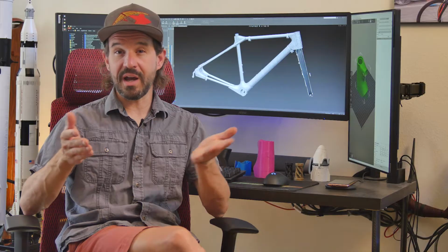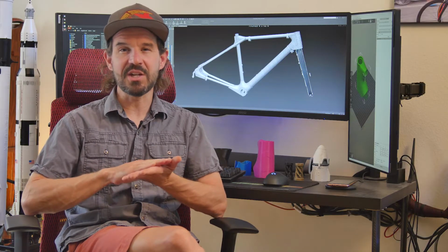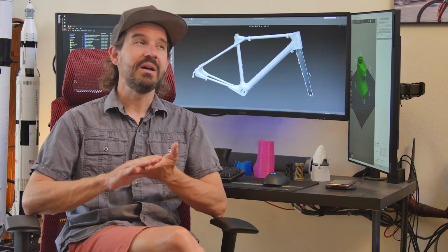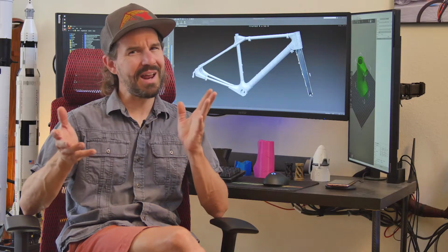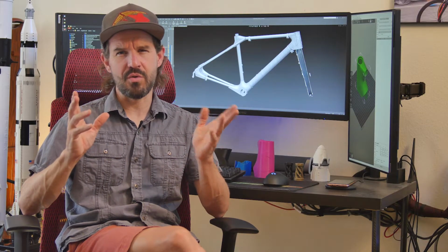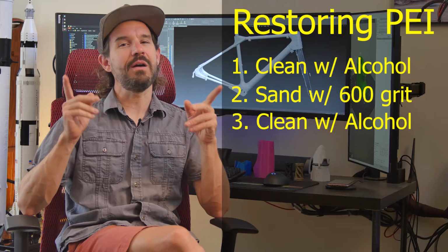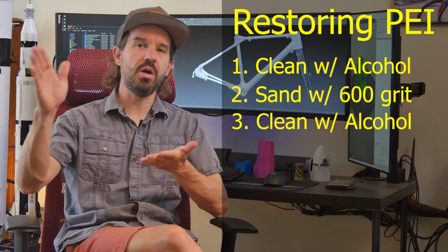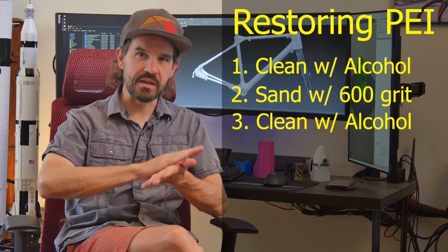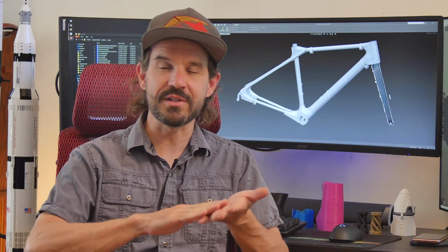You can also try cleaning the PEI sheet with acetone. I've read that that's supposed to work, but I've had mixed results with that, so your mileage may vary. I would stick to cleaning with alcohol and sanding and then cleaning with alcohol. If all else fails, you might need to just replace the PEI sheet. They're not that expensive, but I have found that I've been able to basically extend the life of these sheets indefinitely by just sanding the surface down with 600 grit sandpaper and cleaning with alcohol.